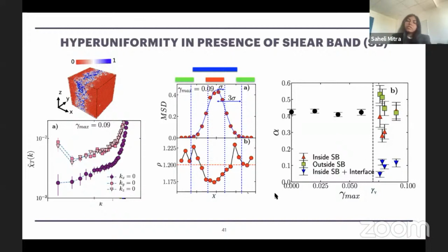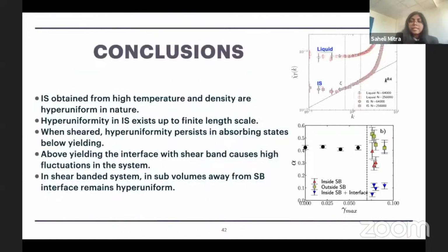So to conclude, what we have seen so far is that inherent structures obtained from a high density, high temperature liquid are hyperuniform up to some finite length scale. And as we shear, the system remains hyperuniform in the absorbing state. Above yielding, the system loses hyperuniformity because of the interface formed between the shear band and the outside of the shear band. But separately, the parts inside and outside still continue to be hyperuniform.